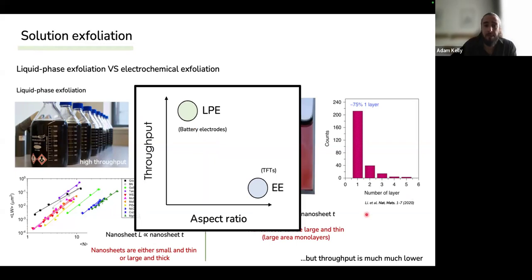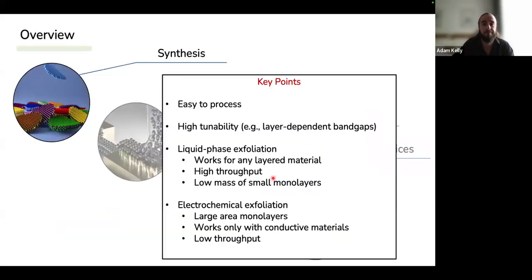So the one thing to take away from this, if we're thinking about throughput versus aspect ratio, is that liquid phase exfoliation has a low aspect ratio, generally somewhere in the range of about 50, but we have a high throughput. Now, the low aspect ratio means you have a high surface area in your printed networks, which is good for things like battery electrodes where you want surface area. When it comes to electrochemical exfoliation, we have a very high aspect ratio, in the range of hundreds to thousands. And this is very, very good for transistors because we have large basal planes.